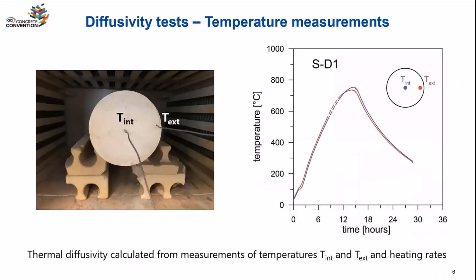So for the thermal test, we looked at measurements of temperature in concrete cylinders. So by measuring the temperature at two locations inside the specimens, and looking at the conduction problem there with axis symmetry, we could derive the thermal diffusivity. And again, what was important here was to monitor closely what was happening not only during heating, but also during cooling. So the thermal diffusivity is a material property that includes conductivity, specific heat, and density, and is the key driver of conduction in the material.